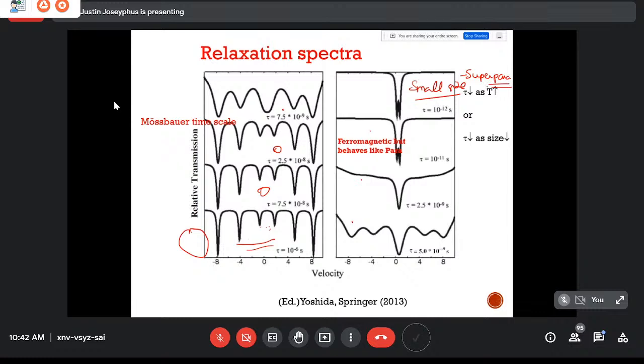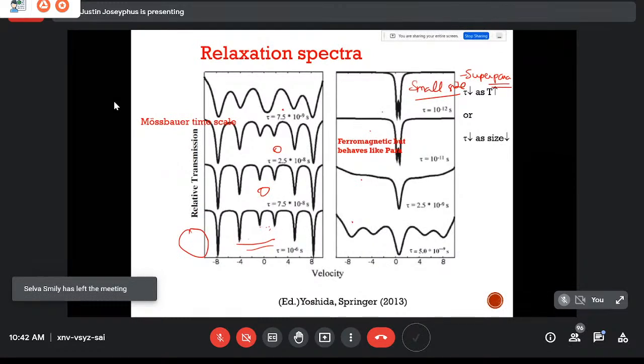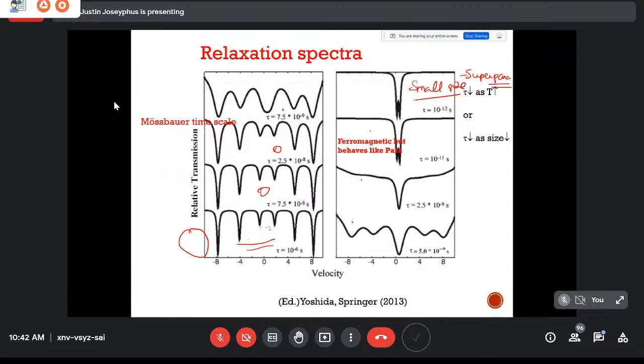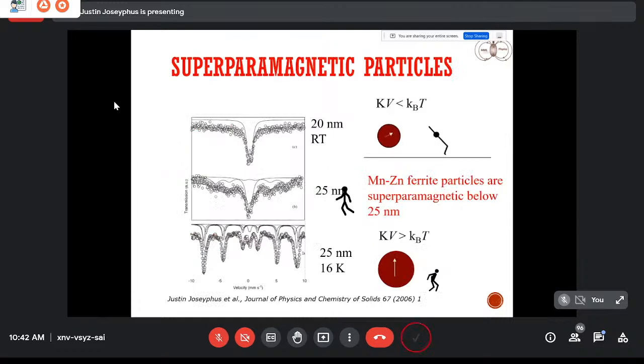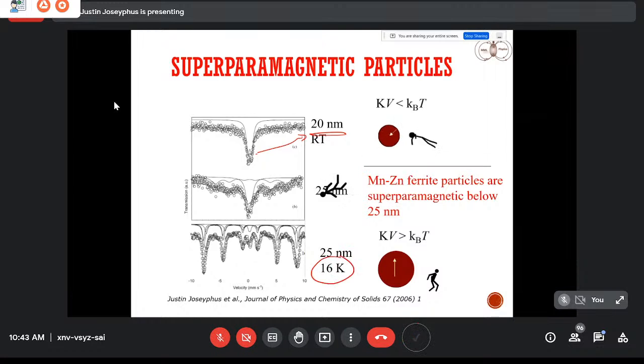Superparamagnetism is a small size effect where the same material which shows a 6-line pattern becomes a double line, doublet pattern when you reduce the size. That has been studied by us. For 20 nanometer manganese zinc ferrite, you have a double line pattern, and for a 25 nanometer particle at 16 Kelvin, very low temperature, you have a 6-line pattern. You have this difference in the line spectrum due to the size effect, because it is showing a relaxation effect.